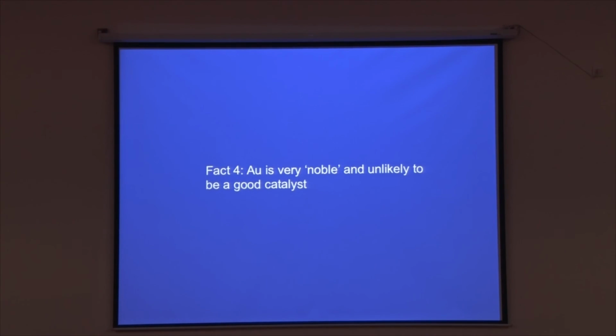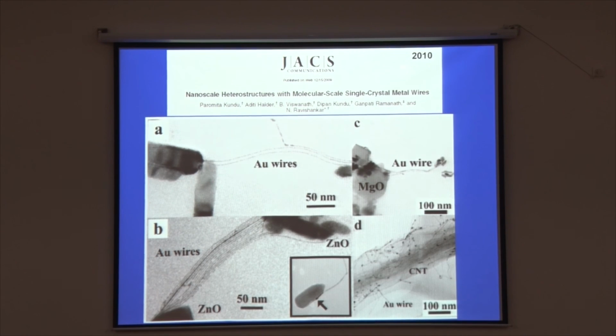And the last part, maybe just a couple of slides. Gold is a noble metal and we do not expect it to be good for any catalysis. Of course, there is the so called Haruta catalyst, where very small clusters of gold are used for carbon monoxide oxidation and so on. So these are actually in the right size to do some kind of catalysis. In addition, we also have a path for electron transport. So there are some interesting things that could happen, but to do any of that, we need to be able to put these wires on different substrates or attach them to different substrates. And so we have been working on making different kinds of heterostructures using these single crystalline gold nanowires.